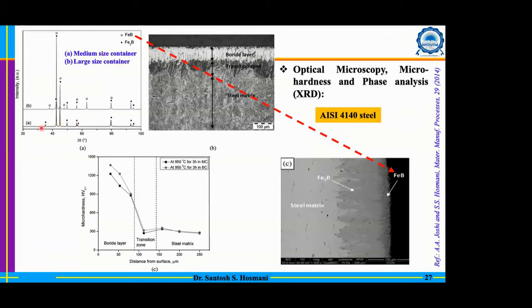You can see in the XRD figure, figure A, that you will not see any peaks corresponding to the FeB layer. That means if your potential is controlled appropriately, you can avoid the formation of the FeB layer. However, if your potential is high, as in the case of the large container, there you can see the clear indication of the FeB layer, which is observed in SEM as well as in XRD.